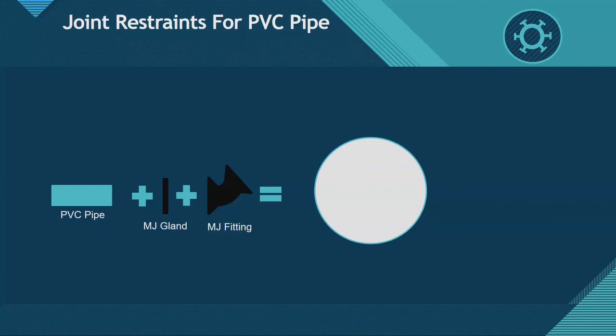If you're going to an MJ fitting, you can use a serrated restraint to go to an MJ fitting. I would never recommend it, but it is possible. I will show you how it's possible and why you will never ever want to do it. You've got your handy dandy fitting, you've got your gasket, and where did my piece of pipe go? There's my piece of pipe. And you've got your pipe. So unlike a wedge action restraint, a serrated restraint is flat on both sides. It's got nothing to compress the gasket.